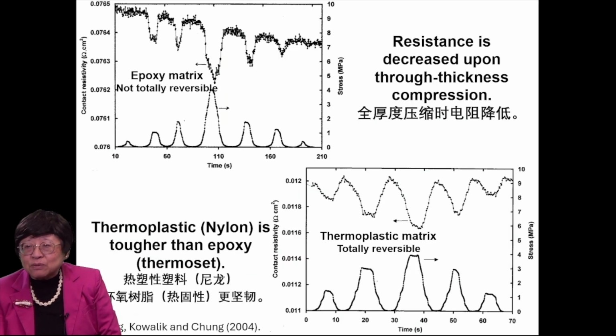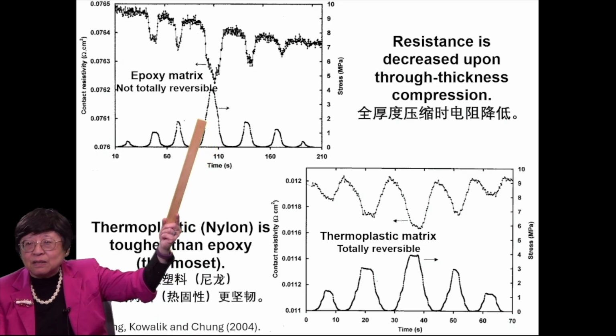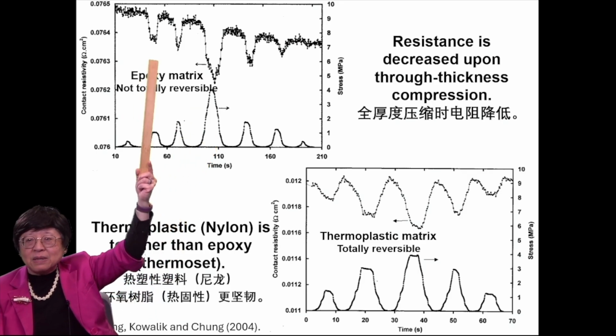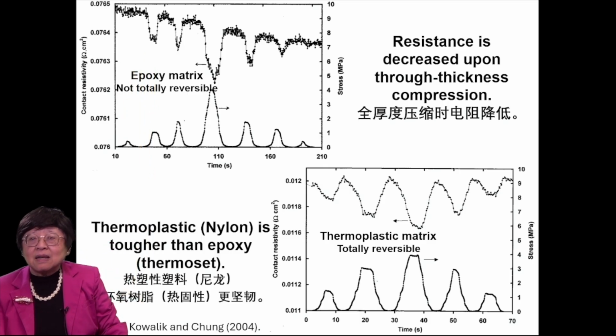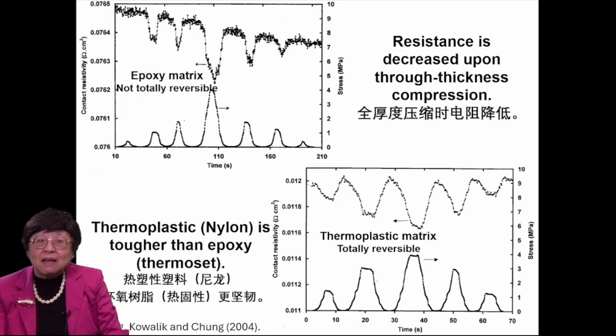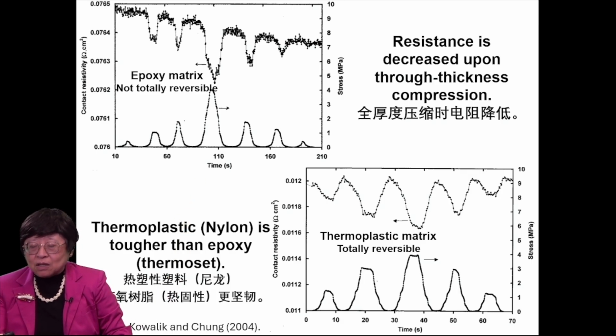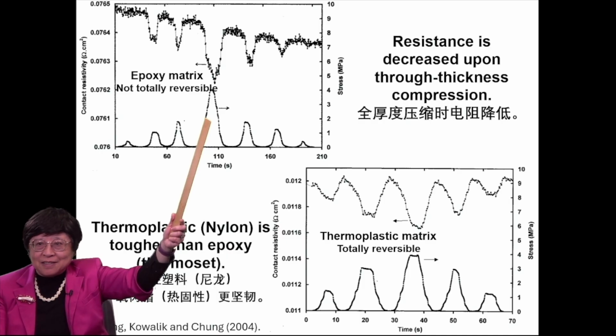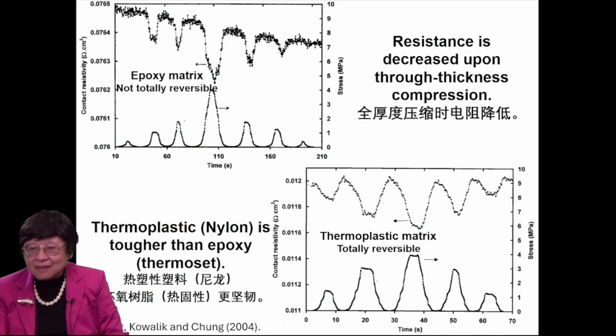So one can measure the contact resistivity of the interlaminar interface during different cycles of squeezing at different stress amplitudes. And every time one squeezes, the contact resistivity decreases because of the increased proximity between the laminae, and so more fiber-fiber contact across the interlaminar interface. And note that this decrease of the contact resistivity of the interface is not totally reversible. And that's not good. That means there's irreversible change in the composite due to this squeezing.